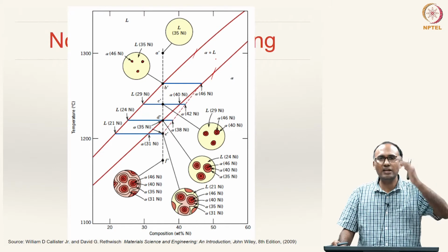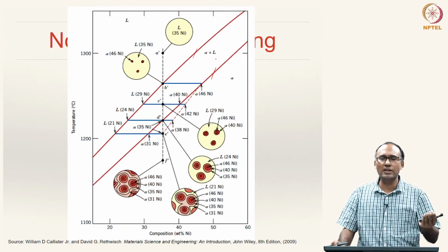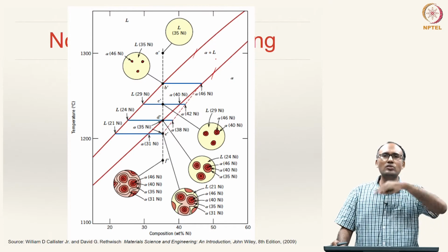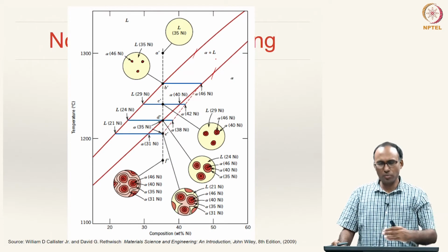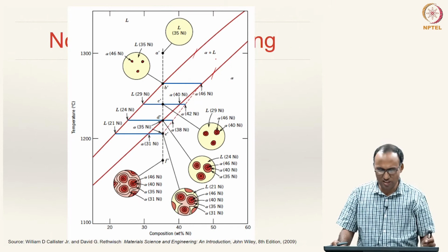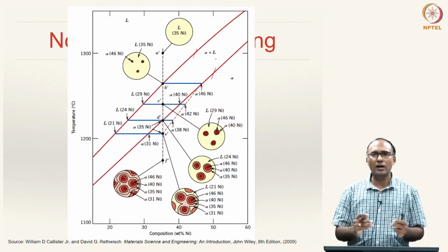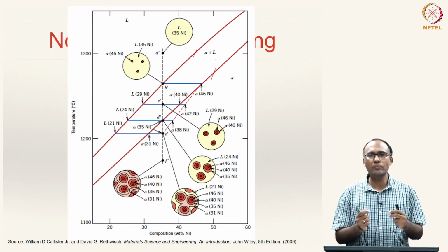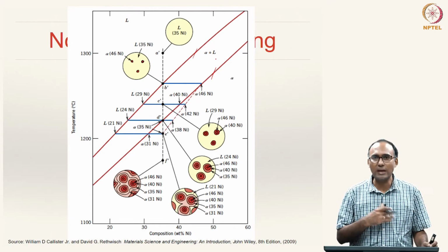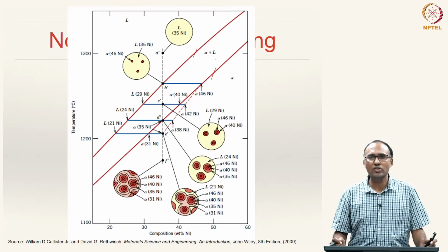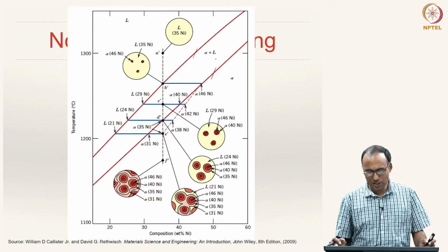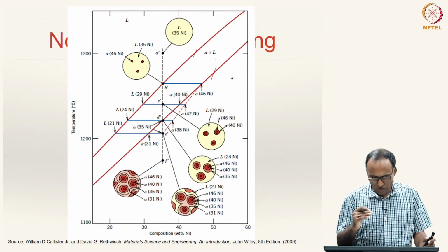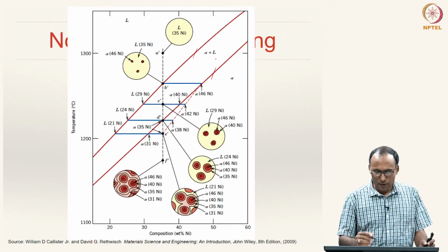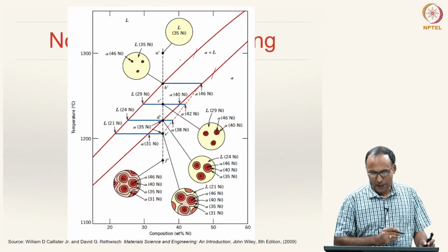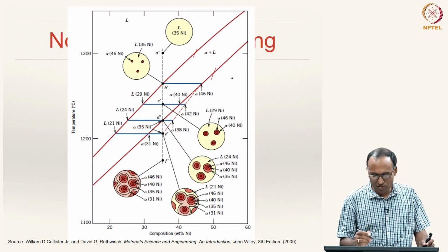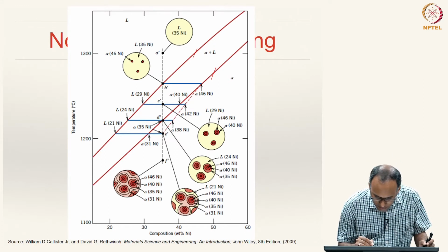The cooling is done in a non-equilibrium manner only in the solid state, but not in the liquid state. That is a reasonable assumption, because in the liquid state you are at very high temperature, right. So, the assumption that equilibrium exists in the liquid state is a reasonable one, but in the solid state you need sufficiently long time for solid state diffusion to take place. So, it is a time dependent process, and hence cooling rapidly is going to change certain things when we are looking at solidification in the solid regime, and hence there is no change in the liquidus line, whereas the non-equilibrium cooling solidus line is represented by this dashed line.